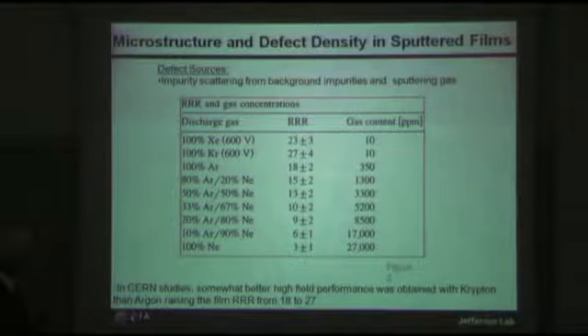And you could lump all the things that cause electron scattering into two groups. One is, in case of sputtered films, the sputtering gas inclusion, and the other would be structural defects from the niobium film itself.